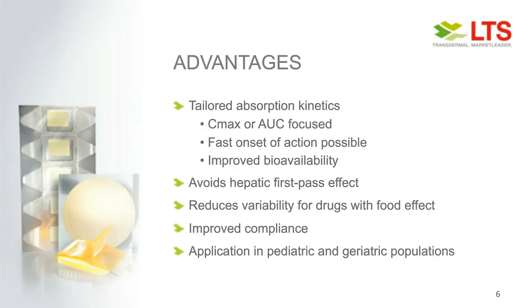If we go to the advantages of oral thin films, we're looking at the pharmacokinetic profiles and absorption kinetics we can modulate with oral thin films. So not just can we be Cmax focused, to have a faster onset of action, which is very often possible, but we can also modulate the PK profile to be a bit more AUC focused, for example, to avoid side effects from a high Cmax, and therefore also very often achieve an improved bioavailability. Another advantage is the possibility to avoid hepatic first pass effects due to the oral mucosa uptake. We can reduce variability for drugs with food effects, and for patients, since there is no water needed and no differences in the application, we think and we have seen we can improve the compliance especially. So as said before, it's a great opportunity to be applied in pediatric and geriatric populations.